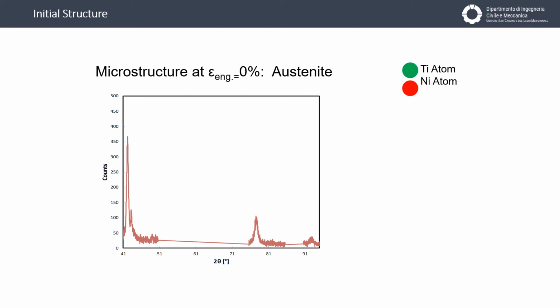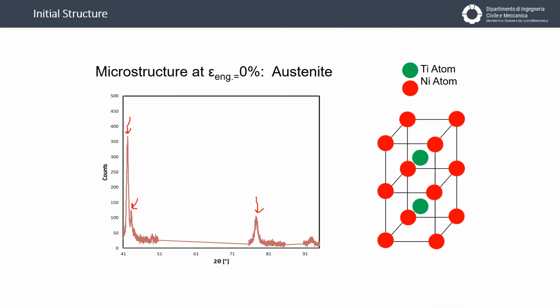In this slide, I show the spectrum of the unloaded specimen. We can see that we have a first peak here, a second peak in this position, and the third in this one. Analyzing this spectrum, we can see that this structure is the structure of a cubic lattice, characterized by the position of nickel atoms on the vertices of the cubes, and the titanium atoms inside of the cubes.